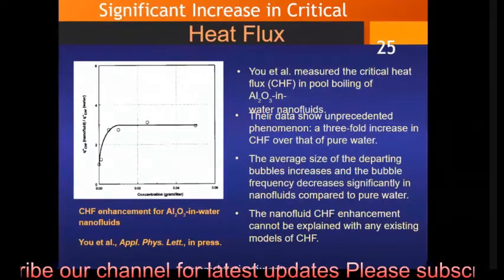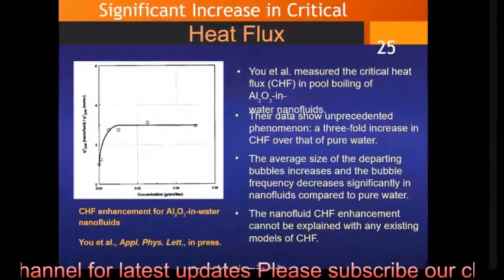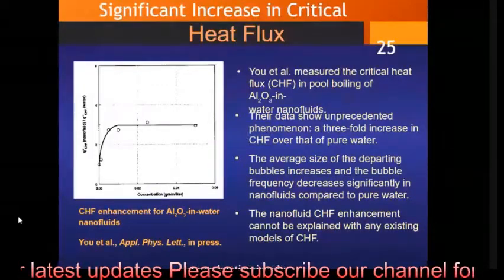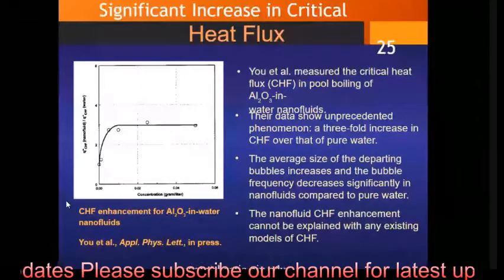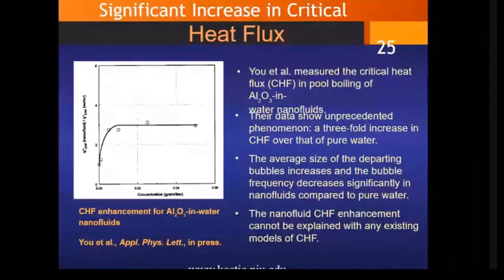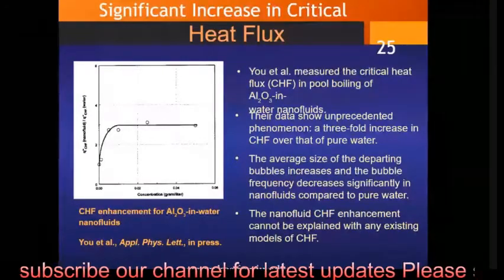The next one is a significant increase in critical heat flux. Normally the critical heat flux plays a vital role in the enhancement of nanofluids. The figure represents basic graphical structures of Al2O3 in water as a nanofluid. But normally, it is predicted that the average size of departing bubbles increases and the bubble frequency decreases evidently in nanofluids compared to pure water. So nanofluid critical heat flux enhancement cannot be explained with any existing models of CHF.